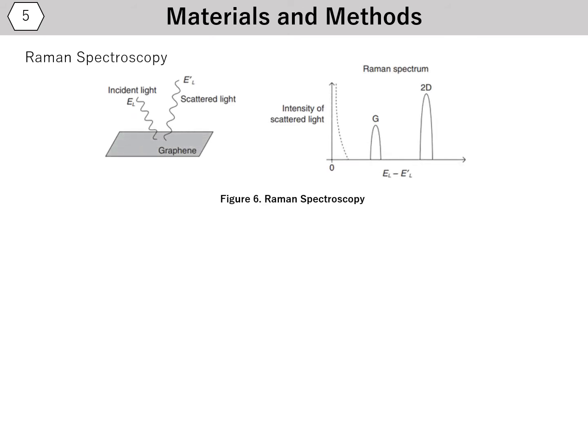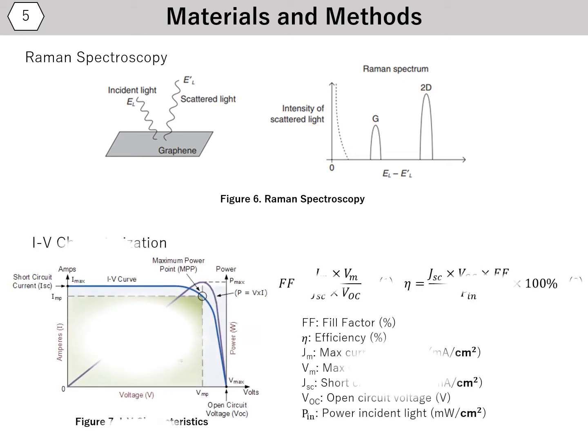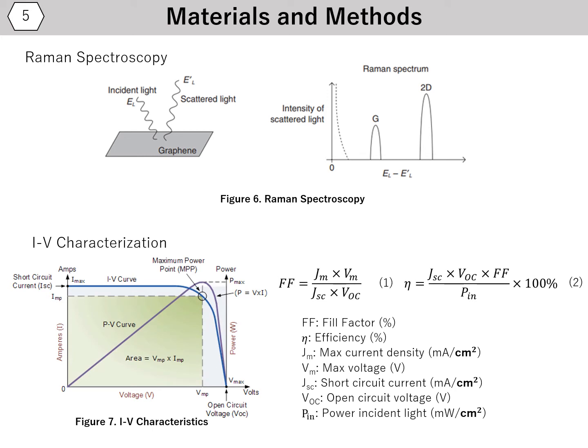With Raman spectroscopy, we can investigate features for carbon such as G-band for sp2 hybridized carbon atom, D-band for defect in carbon ring, and 2D band for graphene characteristic. From IV measurement, we can obtain the fill factor and efficiency of the cell, then we compare using other different electrodes.